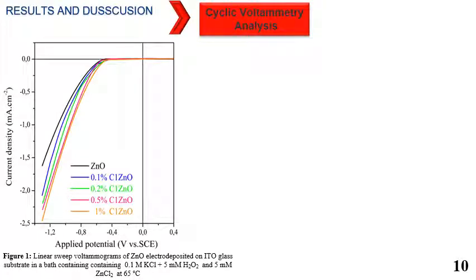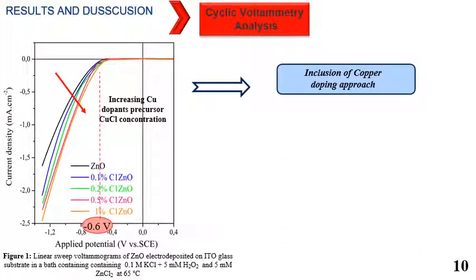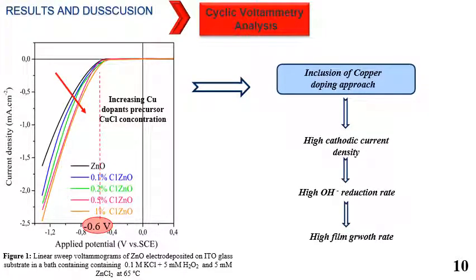This figure shows the linear voltammogram response of the zinc oxide growth solution with different amounts of copper. As can be seen, all the voltammograms show the same appearance, where an obvious cathodic current started to flow near minus 0.6 volt, which was attributed to the reduction process of hydrogen peroxide. It was observed that with copper doping, the cathodic current tended to increase. This revealed the increase of the reduction rate of hydroxide ions, which in turn leads to an increase in the growth rate of copper-doped zinc oxide nanostructures.